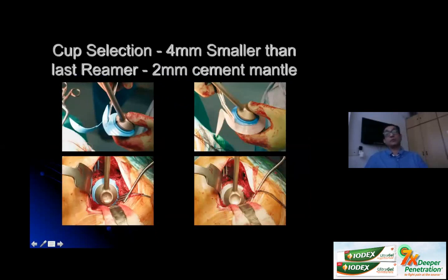The next step would be to select your cup, which is generally 4 millimeters smaller than the last reamer that you used, so as to get about 2 millimeters of cement mantle on all the sides. Take your cup, do a trial positioning of the cup. Again, mark the final position of the cup with some marker like methylene blue, so that after you have inserted your cement and put your cup, you can put your final cup in the position that you want, and really don't compromise on the position. So this is what I normally do.